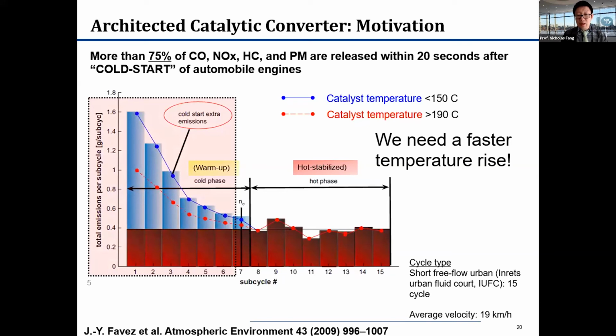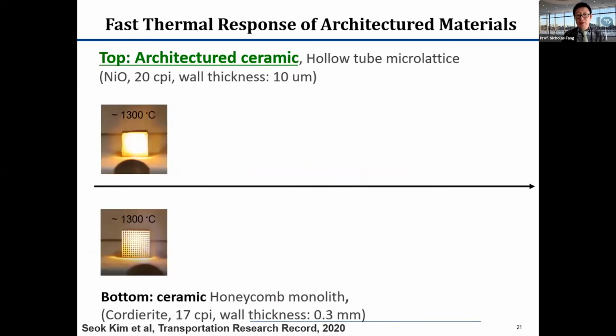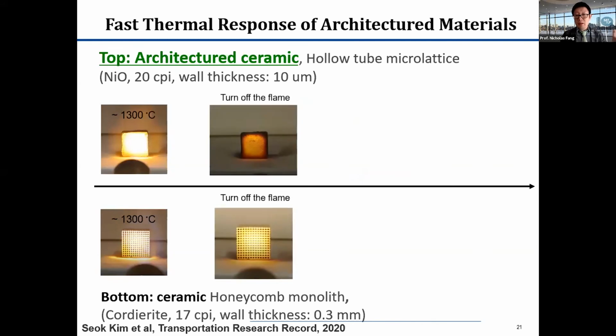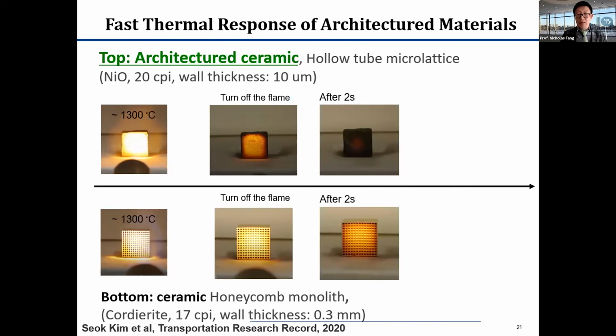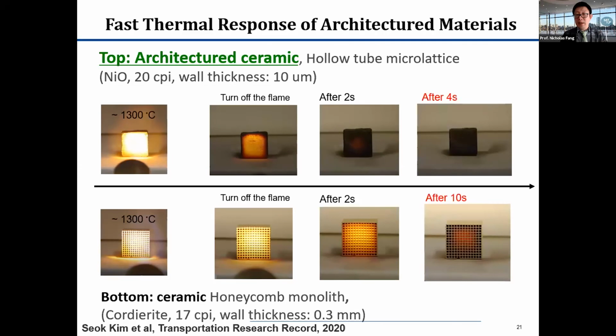So, how do we address this particular issue? It turns out that within that beginning 10 cycles, we really need a substrate that can heat up in a few seconds. And here we show that such architected ceramic materials made by, for example, the hollow tube ceramic, when it is subject to, for example, an immediate heating using, say, a high temperature flame, you see the inverse process here. Once the flame is turned off, after 2 seconds, the lattice already starts to cool, and at the 4-second range, it really goes back to the ambient temperature.